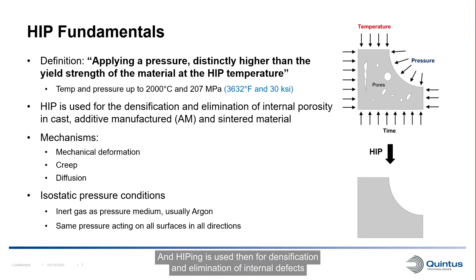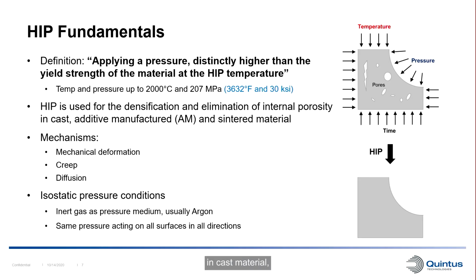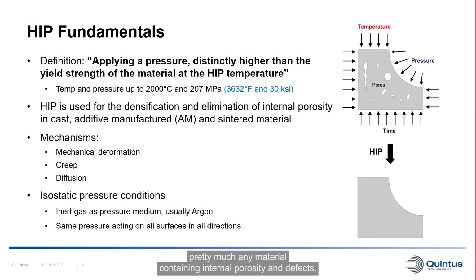Hipping is used then for densification and elimination of internal defects in cast material, additive manufactured material, and sintered material. Pretty much any material containing internal porosity and defects. The mechanisms working during the hip process are mechanical deformation, creep, and diffusion. And for the isostatic pressure condition, we are using an inert gas as pressure medium, and this gas is then pressing on the components on all surfaces in all directions with the same pressure.